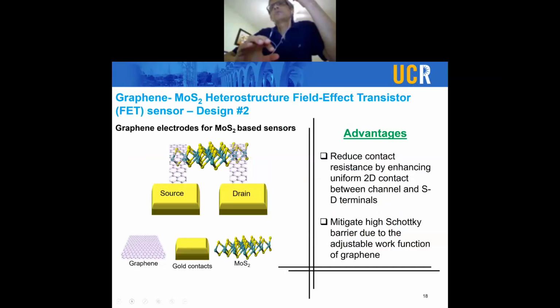The second thing we wanted to do was to look at trying to lower the Schottky barrier between the graphene and MoS2 and the gold and MoS2. To do so, we decided to look at a second design, design number 2, where instead of what people usually do, which is to put the gold electrodes on the top of MoS2, there is a big work function difference between the gold and MoS2. We thought, why not take advantage of the fact that we have graphene, which is a good conductive material, and as I said earlier, it's semi-metallic.